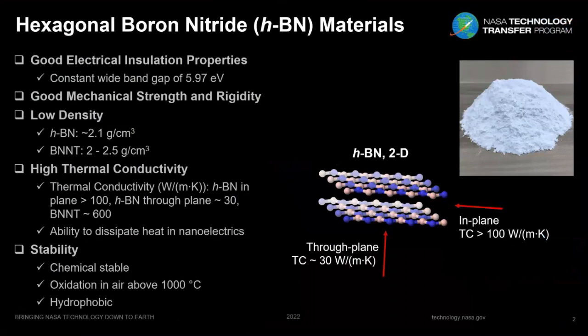Thank you. Hexagonal boron nitride is a beautiful white powder as shown here in the picture that has become one of the most significant ceramics today due to its great properties and possibilities of applications in many different industries, including aerospace. That is the one that we are studying here at GRC. Among the great properties, there are good electrical insulation with a constant band gap of almost 6 electron volts. It has great mechanical strength and rigidity, also a very low density. It has high thermal conductivity with in-plane hBN having more than 100 watts per meter Kelvin and through plane around 30 watts per meter Kelvin. And in boron nitride nanotubes, for example, it also has 600 watts per meter Kelvin carrying it through the length of the tube. So those are very high values.